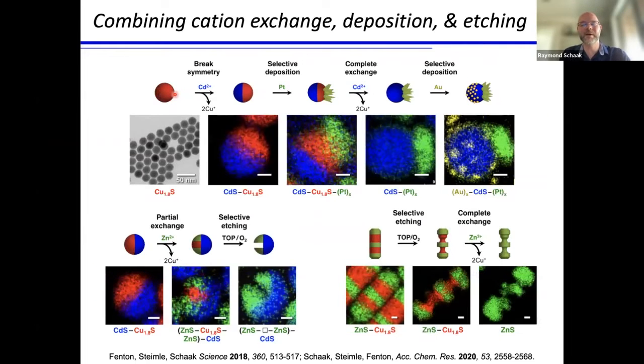And so I'm not going to dwell on this, but I just want to show there's a lot more that can be done when you start taking this partial sequential cation exchange and integrating it with other transformation pathways of nanoparticles. For example, breaking the symmetry of a sphere and then using the different surfaces for preferential deposition, the seeded growth part. You can merge seeded growth with partial cation exchange to begin growing different materials at different ends.